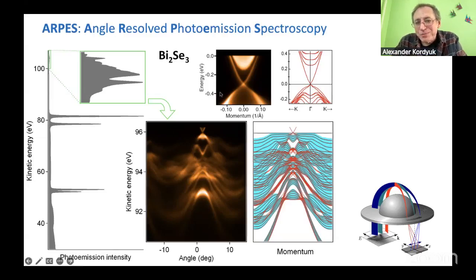And I was very impressed when this sample goes to the fast entry with the vacuum two orders of magnitude worse than in the measuring chamber. And then I wanted to put it back and to see that the spectra almost disappear, but these surface states are still there. They even go to the Fermi level. And then with time it goes back, when some dirt evaporated from the sample surface, and therefore the surface states, they are extremely stable in this sense.